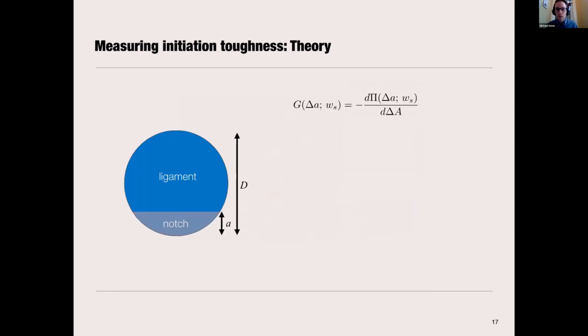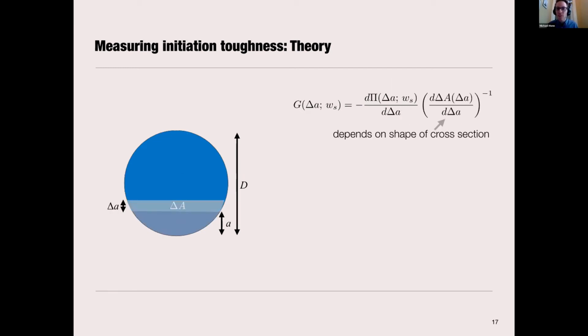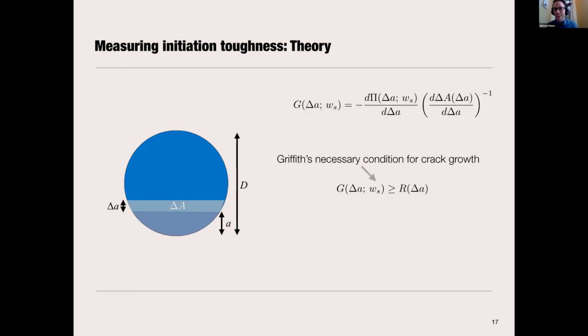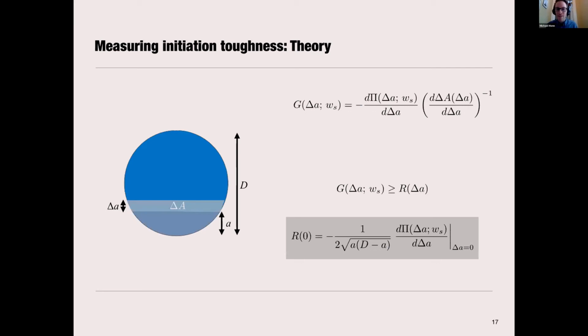For the initiation toughness, we go back to the energy release rate, which is the derivative of the potential energy of the system by an increment in crack area, delta big A. And this depends on the shape of the cross-section. So if we recast this as a derivative of potential energy with respect to a crack length, you also have this second term on the right-hand side, delta big A over delta small a, which captures the cross-section, which is a little complicated to use, the circle rather than a rectangular cross-section. Griffith's necessary condition for crack growth says that crack growth can occur when your energy release rate exceeds your crack growth resistance. And using that and taking delta A going to 0, we can write this equation so your initiation toughness, R0, will look something like this, where the first term captures that geometry effect, and the second term is that change in potential energy.